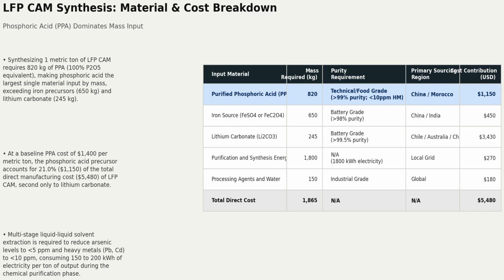Achieving battery-grade purity requires reducing arsenic levels to below 5 parts per million and heavy metals to below 10 parts per million. This purification process relies on energy-dense solvent extraction, consuming up to 200 kilowatt-hours of electricity per ton. Without localized, high-volume purification capacity, the Western battery supply chain remains highly vulnerable. The transition to domestic electric vehicle manufacturing cannot succeed without securing this heavy chemical processing node.